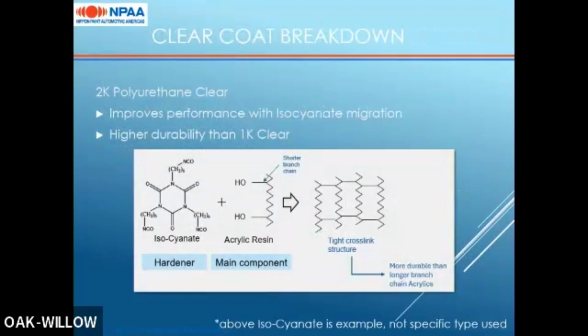In the clear coat we have, we use a similar isocyanate to the one pictured here. This is just an example, combined with an acrylic resin that is designed for a shorter branch chain. This creates a tighter cross-link structure, which is more durable than a longer branch, which is typically used more for polishability performance.